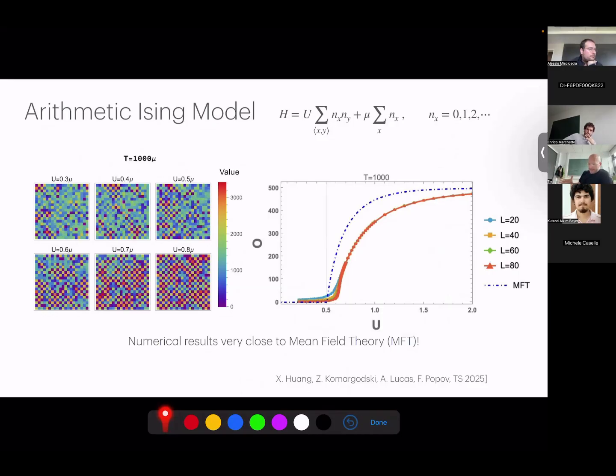On the right, you will see an order parameter as a function of u for temperature equals 1,000 mu. Everything is in units of mu, so mu is set to 1, and all dimensionful quantities are in units of mu. These are lattice results, lattice points for various lattice sizes. As you can see, if u is small at this high temperature, there doesn't seem to be order. The order parameter is 0 for this symmetry breaking. And then at some point, it starts rising. You can check critical exponents, and you find that they are Ising-like, because the relevant symmetry which is broken is Z2. It's a translation symmetry mod 2.